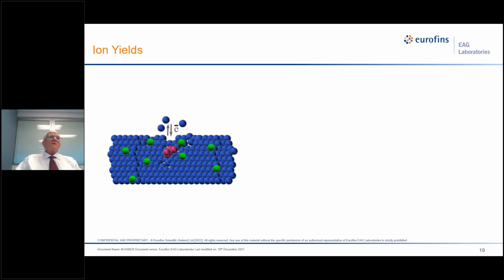So here's how we can get around that. We have a primary ion, the purple guy. He comes in and gets buried in the sample and ejects some particles, positive and negative ions, but mostly neutral atoms. And here we have some dopant atoms. There are a number of things we want to point out, because people have asked, well, what about the depth resolution between SIMS and, say, XPS? Well, XPS has an escape depth of about 25 angstroms, and that's a 1/e depth resolution. SIMS is kind of depicted there. Most of the detected or sputtered atoms are emitted from the top 1 or 2 monolayers.